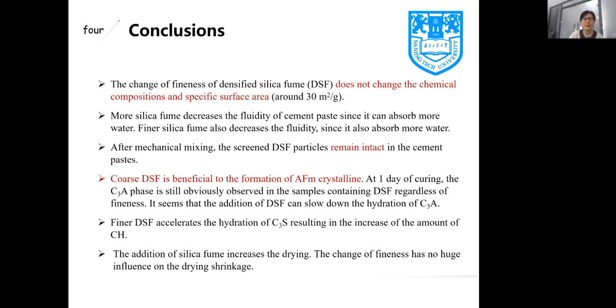Firstly, the change of fineness of densified silica fume does not change the chemical compositions and the specific surface area, but the fineness of densified silica fume changed the workability of cement paste, such as more silica fume decreases the fluidity of cement paste since it can absorb more water. Finer silica fume also decreases the fluidity since it also absorbs more water. After mechanical mixing, the sieved densified silica fume particles remain intact in the cement paste.